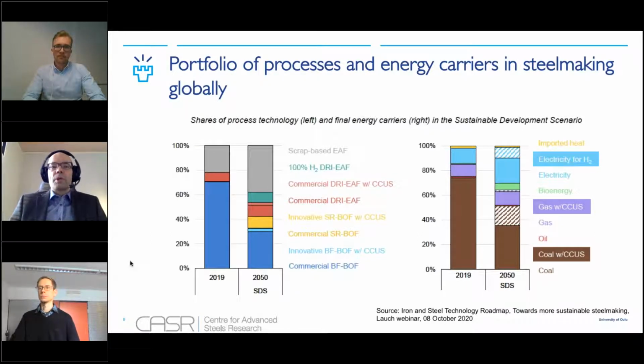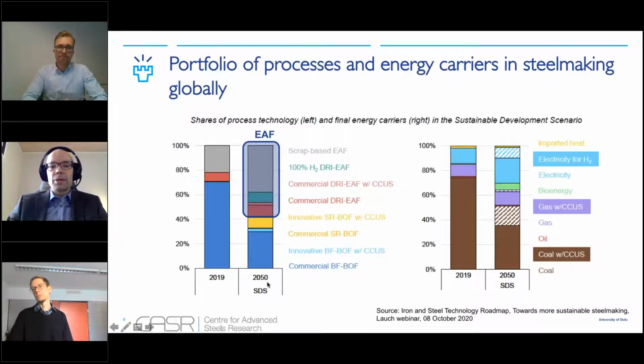If you look at the portfolio of processes and energy carriers in steelmaking on a global scale, here on the left side, we can see that in 2019, approximately 70% of steel is produced based on the commercial blast furnace BOF route, and approximately 20% by scrap-based electric arc furnace, and less than 10% by commercial DRI. If you look at the estimations concerning 2050, we see that approximately 60% of production will be based on the electric arc furnace route.